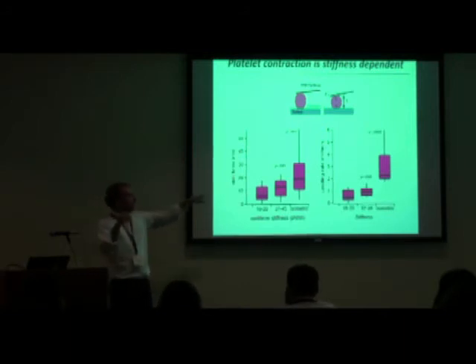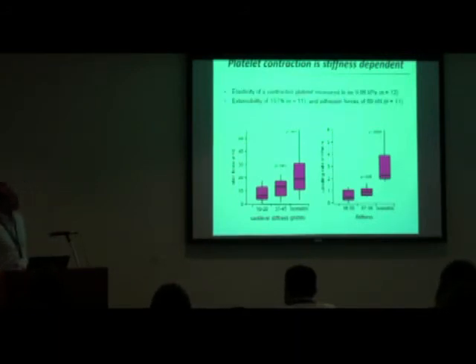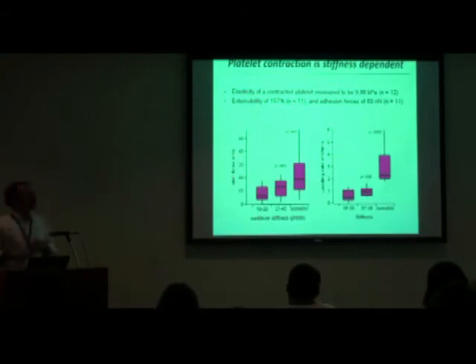Well, I don't know the answer, but I'll give you a hypothesis that we have. And that is, if you have a heterogeneous clot, which is most likely, there's probably not a great way of creating a clot that is completely uniform in its density of fibrin or its density of platelets. So you're bound to have different amounts of contraction and different mechanical properties. If you have a platelet that can pull harder on a stiffer clot, you have a greater chance of uniform contraction of that clot despite it being heterogeneous. So that's our thinking for why this might be of interest. We were able to measure the elasticity in this configuration, about 10 kilopascals, and extensibility. So even though it's contracted, it's extensible. It can be stretched without breaking.